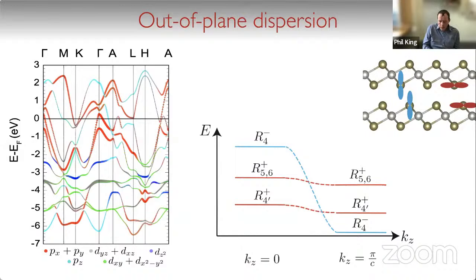Okay, and so you see when we have this that quite naturally, as long as the out-of-plane dispersion of these pz-derived states is larger than the crystal field splitting of the pz from the pxy pair, then we'd expect this pz-derived state to disperse downwards and cross through the px and py-derived states as a function of the out-of-plane momentum in the system.